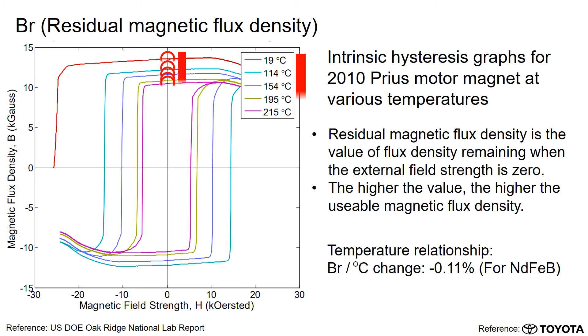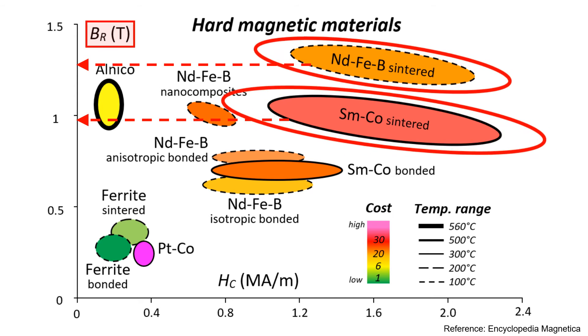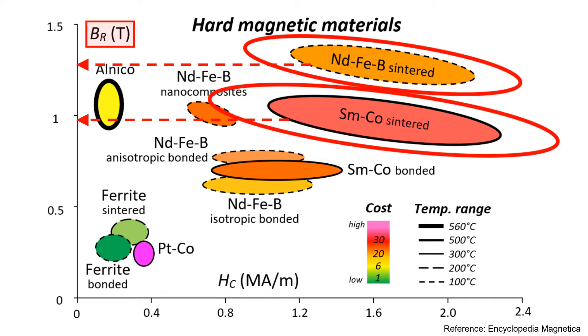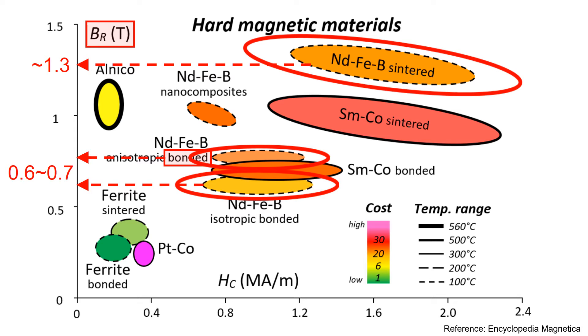It is important to note that Br tends to decrease with rising temperatures. Indeed, Br is influenced by the magnetic material itself. As you can see from this graph, neodymium iron boron tends to have higher Br compared to samarium cobalt. Also, Br is significantly affected by the manufacturing process. For example, in the case of the same neodymium iron boron material, if it is sintered, the resulting residual magnetic flux density Br tends to be higher compared to bonded neodymium iron boron material.